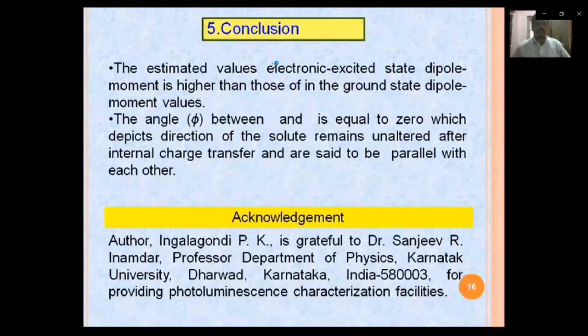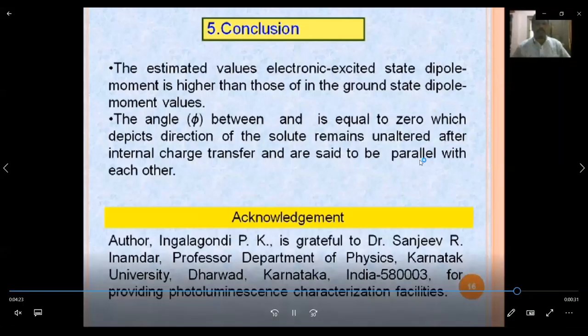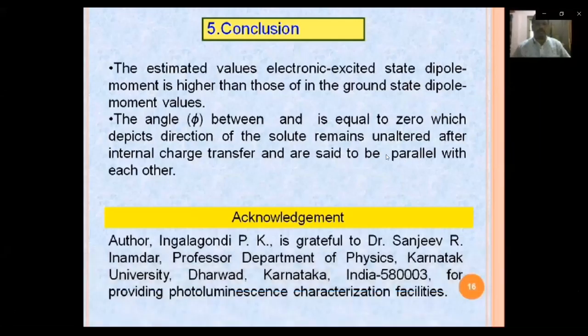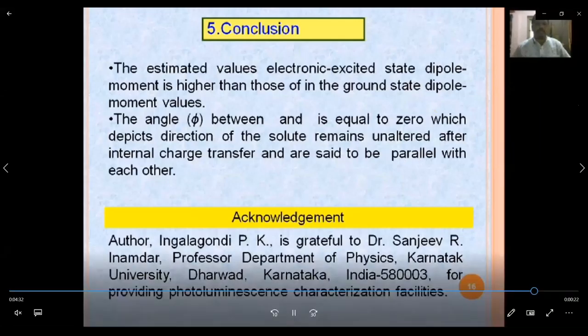Let's come to the conclusion. The estimated value of the excited state dipole moment is higher than that of the ground state dipole moment. The angle between the ground and excited state dipole moments is equal to zero. It depicts that the direction of the dipole moments is unaltered after internal charge transfer, and they are parallel to each other.